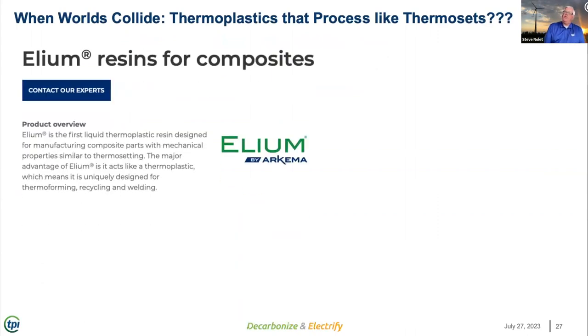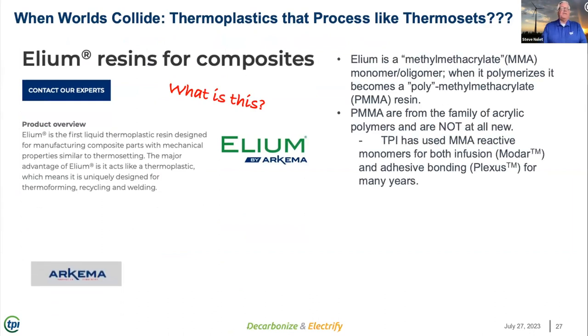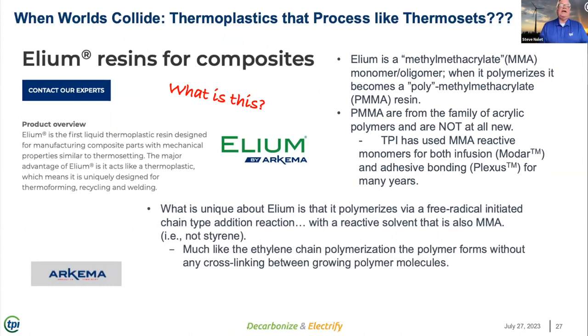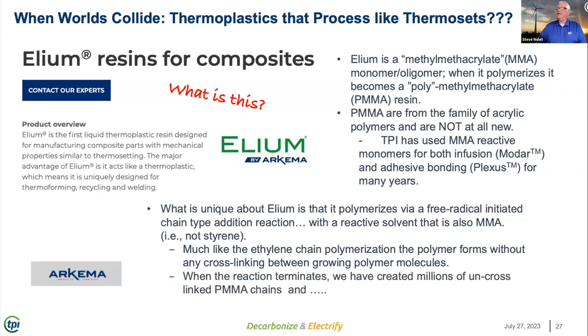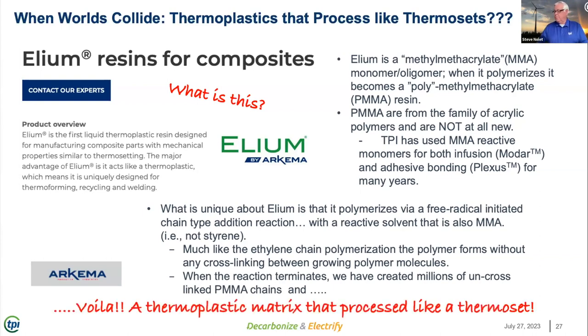Finally, I'm going to talk just really briefly about liquid thermoplastic resin, Elium. You're probably familiar with it, a liquid thermoplastic material. Its low viscosity allows it to be utilized much like a thermoset material. But when it polymerizes, it doesn't cross-link. As a result, we have an in-situ polymerization without cross-linking. And by the way, that's a thermoplastic material, a polymethyl methacrylate thermoplastic, that allows us to build thermoplastic parts with very, very favorable properties. In fact, it's nearly a drop-in replacement for the epoxy systems we build in blades. Thermoplastic material processed like a thermoset.